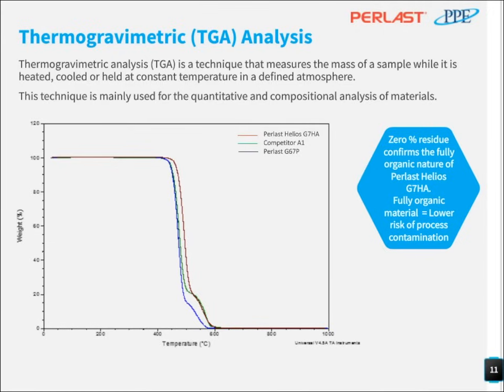There is an interesting point here I need to mention. The initial weight loss temperature of Perlast Helios G7HA material is slightly higher than the other materials, which can be interpreted as this material has better high temperature stability, as you can see on the red line on the TGA curves.